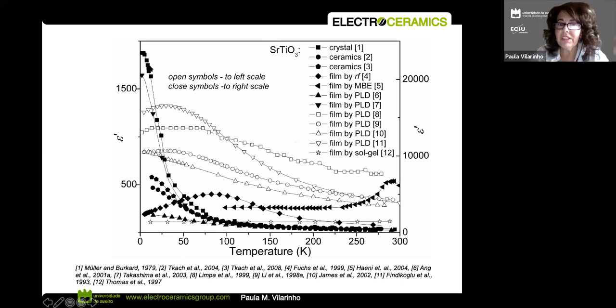And what is represented here is the behavior of a single crystal. So if you follow this line, you see that the permittivity is high, and then it goes down, down, down, down with the temperature. These are crystals. The highest permittivity is observed for crystals, for single crystals. So then if we prepare ceramics, and the difference between ceramics and single crystals, I'm going to say, is that at least we have grain boundaries, then this drops. You see, that's the effect of the grain boundaries. But if we move to films, then the drop is even bigger.